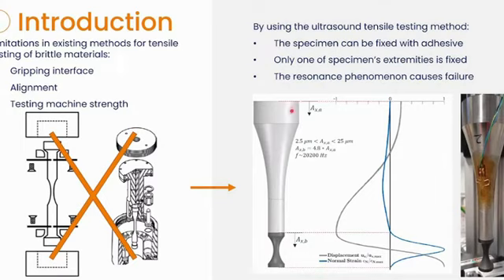In this machine, there is a range of amplitude of vibration between 2.5 and 25 micrometers that can be applied at the horn's base, which is then amplified by the machine by 4.8 times. The interface between the horn and the specimen has a normal strain equal to 0, which allows the specimen to be fixed at the horn by a simple adhesive.